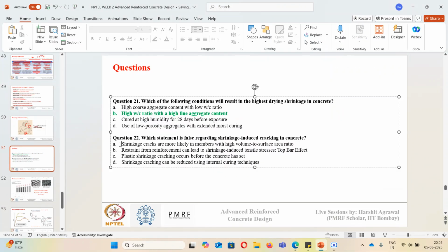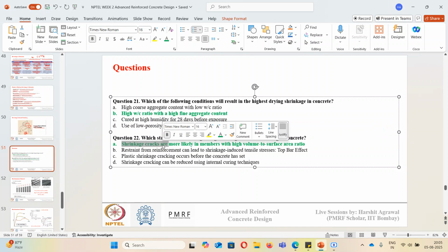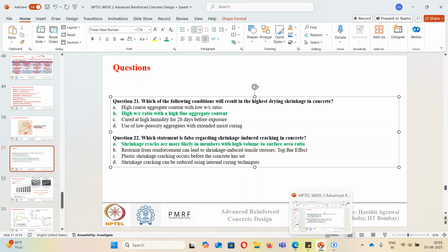So the correct answer will be A. If you see, it was clearly mentioned here. Shrinkage cracks are more likely in members having high volume to surface area ratio. This is not true. Why? Because the higher the volume to surface area ratio, the lower the surface area. If there is low surface area, then there will be low chances of shrinkage cracks because there is less exposure to the environment. Okay, so shrinkage cracks are more when there is low volume to surface area rather than high volume to surface area. Just focus on the surface area part. Surface area is important for both creep and shrinkage. Okay.